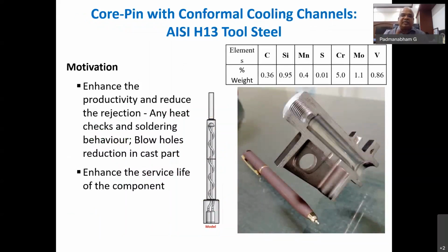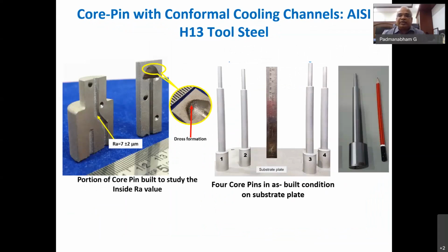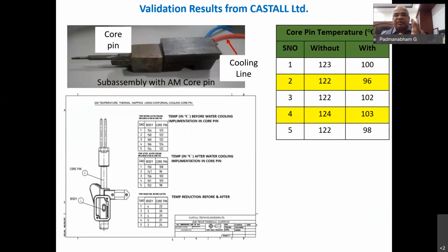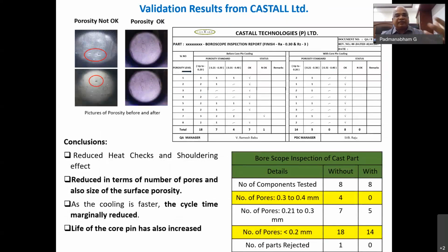You can see the spiraling cooling channel and a semicircular or hemispherical top end that you can see in the picture. And this gives you effective cooling. We have made this using additive manufacturing, and this has been put in actual pressure die casting industry. And you can see without cooling channel and with cooling channel, the core pin temperature is less by about 20 degrees, resulting in less of heat checks and porosity. And that's almost 30,000 shots already done, and industry is happy with this.